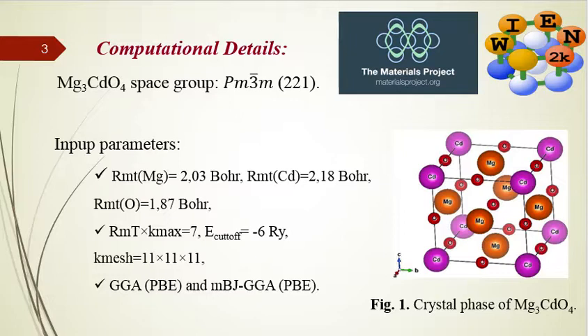Like I mentioned before, this work is based on the density functional theory implemented in the Wien2k code. The exchange and correlation potential is treated by the generalized gradient approximation, and the electronic properties are corrected using the modified Becke-Johnson correction.